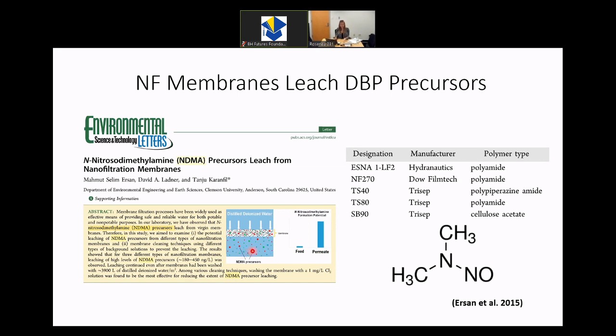So they use something called a formation potential test, which means you take the sample post-membrane treatment and you react it with a disinfectant. What they used was chloramine. So why react with a disinfectant, and why does that help you see if you don't know what you're looking for anyway? What this helps you do is that the disinfectant will likely, if something is there, react similar to how the disinfection byproducts formed when natural organic matter reacts with disinfectants. This chlorine, or chloramine in this case, reacts with whatever is coming off of that membrane, and then we have methods to measure that.